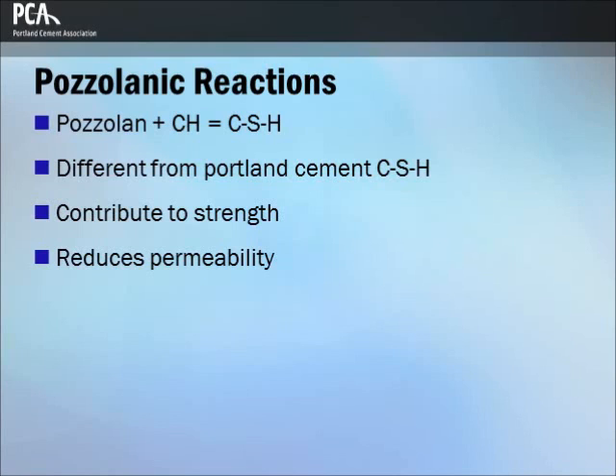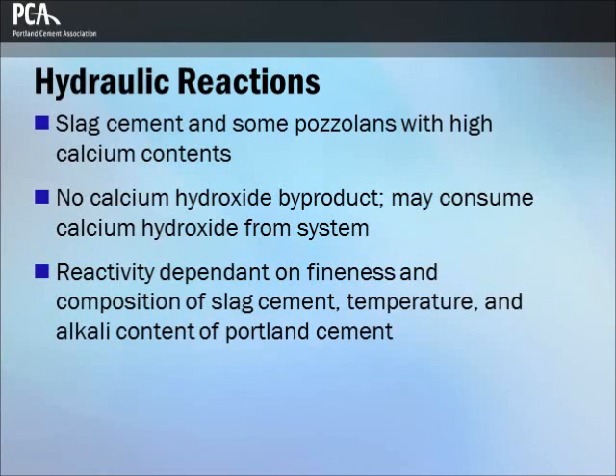A pozzolan will react with calcium hydroxide to form calcium silicate hydrates. The CSH from pozzolanic reactions is not the same as Portland cement CSH, but does contribute to strength and helps lower the permeability of the hardened material. Slag cement is referred to as a latent hydraulic material, meaning that it will hydrate when mixed solely with water, but the process is typically slow. Some fly ashes and natural pozzolans contain enough calcium to possess latent hydraulic properties. Latent hydraulic materials benefit from chemical activation from calcium hydroxide and alkali hydroxides.